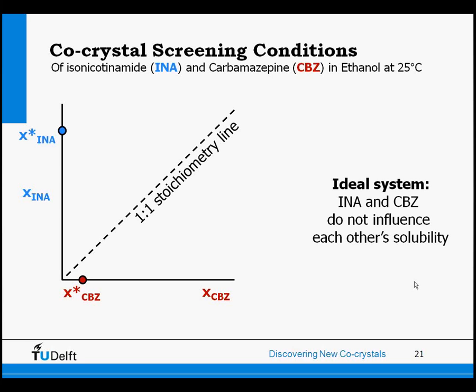So now we can assume that we have an ideal system, and that means that isonicotinamide and carbamazepine do not influence each other's solubility. So that means that we can draw solubility lines in this diagram. One is a horizontal line for isonicotinamide solubility, so it will be constant even though we add carbamazepine to the solution. And the same is for carbamazepine, so that will be a vertical line, and they cross each other somewhere. So within this square given by the blue line, the red line, and the axis, you will have a solution if your co-crystal is not much more stable.